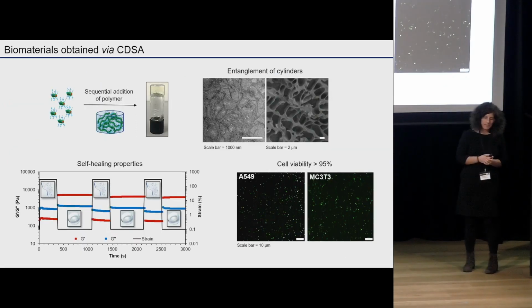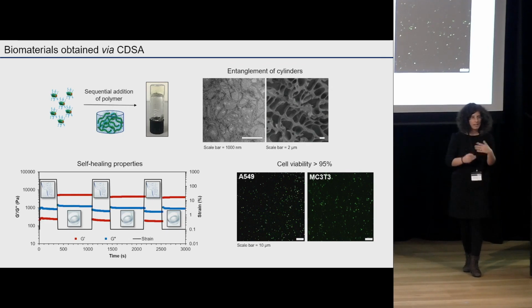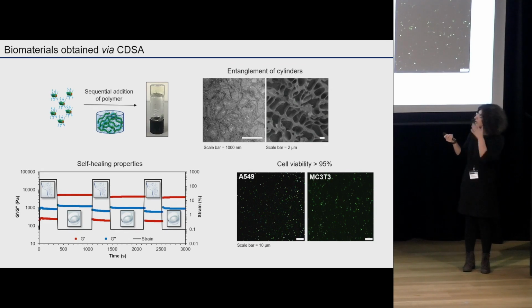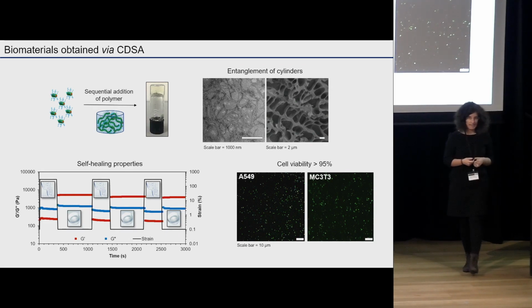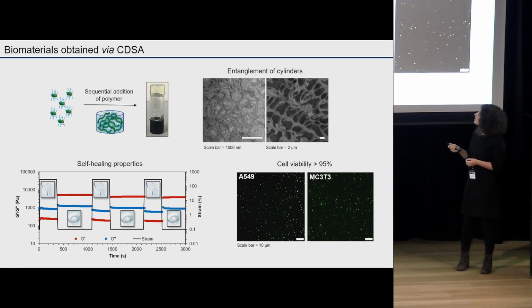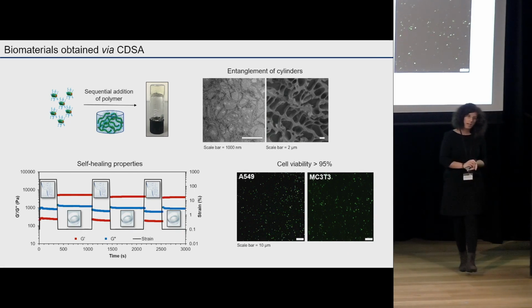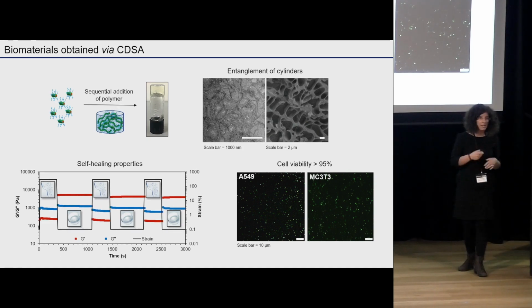What we showed as well was that by continuously adding polymer and growing these nanostructures, we can form a macromaterial, a hydrogel in this case, that is simply formed by entanglement of nanoparticles. This hydrogel has self-healing properties, so you can crush it, and the hydrogel structure is disrupted, so it behaves more like a liquid. And then when you release the force, it comes together as a solid. You can do that in a cycle, and so you can show that it's a self-healing material.